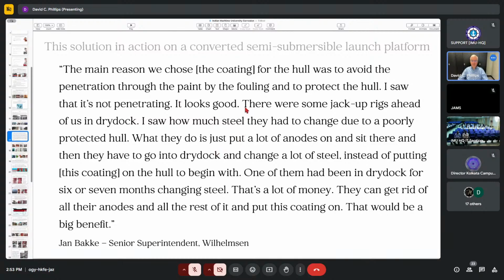And then he made some general comments, because he was very aware of the industry in general. He said there were some jackup rigs ahead of us in dry dock. I saw how much steel they had to change due to a poorly protected hull. What they do is just put a lot of anodes on and sit there. And then they have to go into dry dock and change a lot of steel instead of putting the coating on the hull to begin with. One of them had been in dry dock for 6 or 7 months changing steel. That's a lot of money. They can get rid of all their anodes and all the rest of it and put this coating on. That would be a big benefit. So this is a common situation in the industry where, due to corrosion, a lot of steel replacement is required. And he's saying from his experience that the solution would be to use this type of coating, throw away the anodes, and they'd be fine.